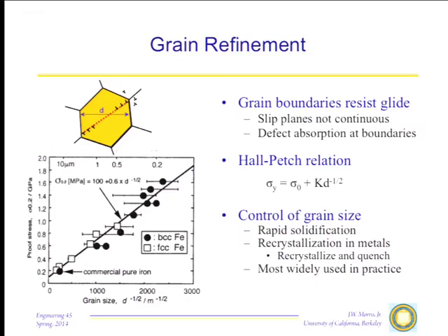The easy way to control the strength, since you're at high temperature, is that when you deform it, it recrystallizes. Recrystallization is, with a little bit of Kentucky windage, a predictable phenomenon. So if you put it through a deformation, through a pair of these rolls to squash it down, you can do a pretty good job of predicting at what temperature after that deformation it's going to recrystallize, and how long it's going to take. So you deform it, the sheet comes out from the roll, and it starts recrystallizing at a certain rate, so you know how long it's going to take to recrystallize and for the grains to grow to the grain size you'd like, and you can translate that into distance ahead of the roll.